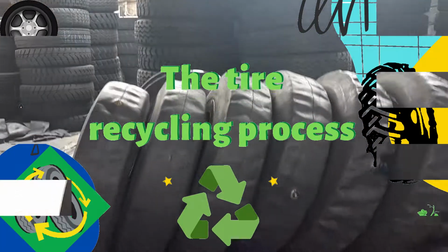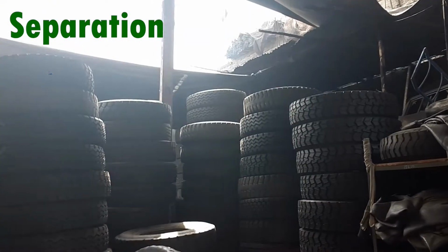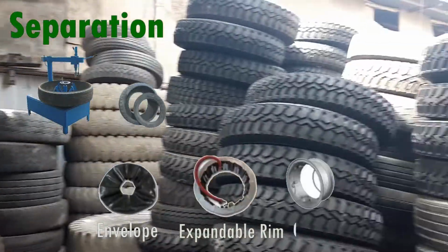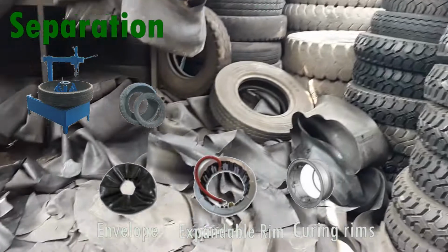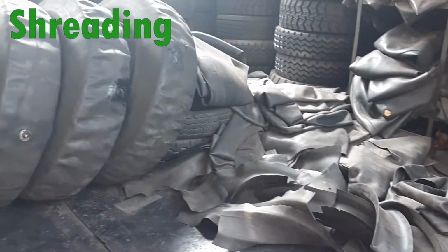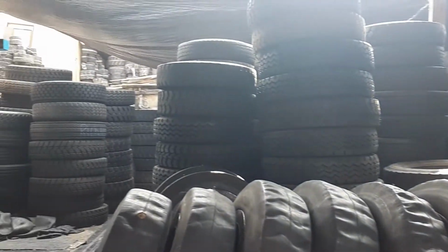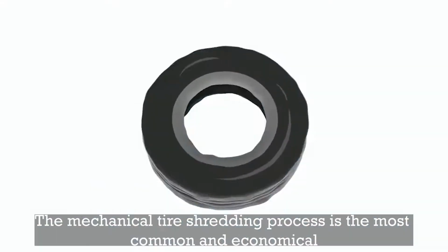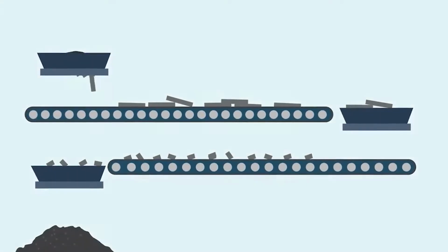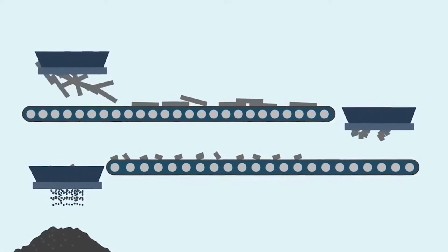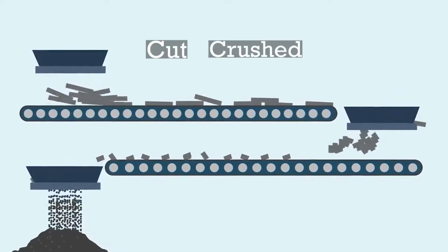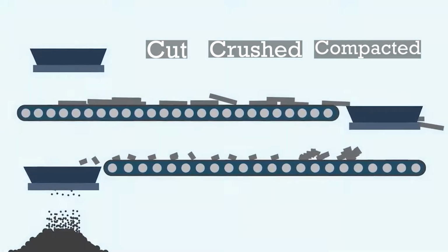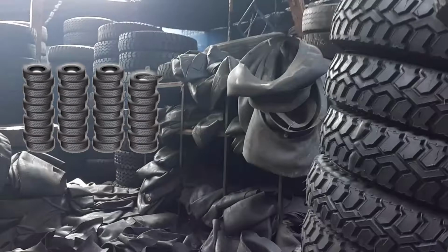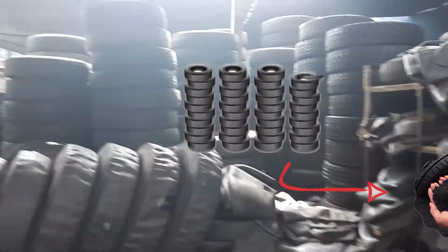The tire recycling process consists of separation. Using specialized recycling machines, the rubber is effectively separated from other materials and dirt that used tires may have. Shredding can be done in different ways, mechanically or chemically. The mechanical tire shredding process is the most common and economical. It allows reducing the volume of the tires to the maximum without using chemicals or adding heat. The used tire is passed through a continuous line where it is cut, crushed, and compacted until the tires are reduced to a size so small that it looks like black rubber sand, in different ways depending on the use that is going to be given later. In the case of concrete, it is reduced to a size of 6 millimeters, replacing the coarse aggregate.